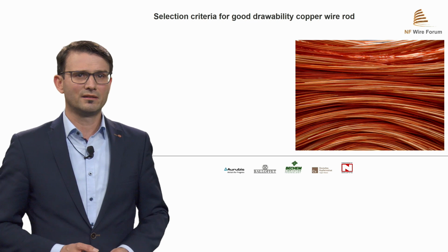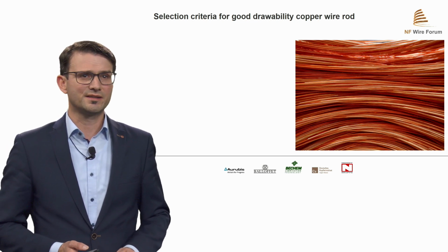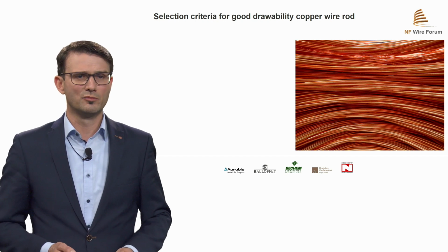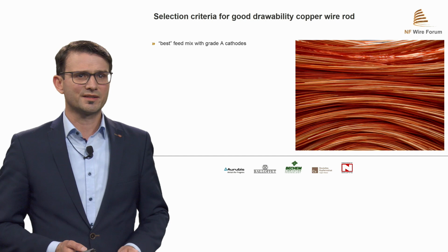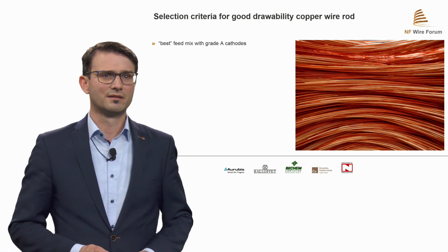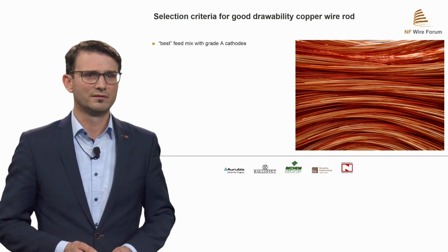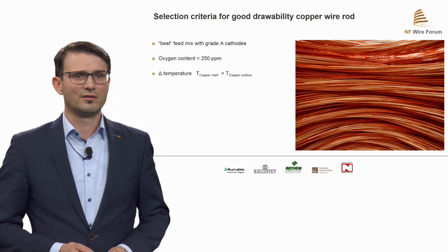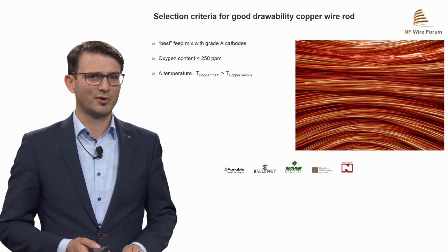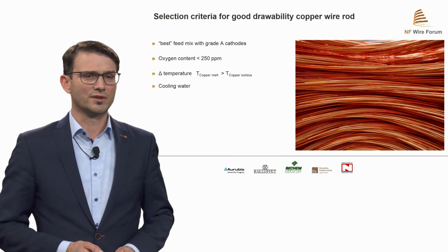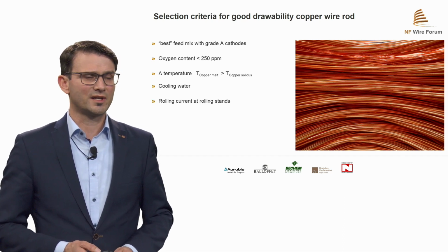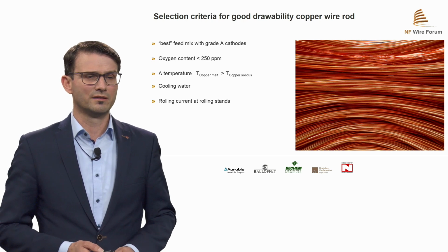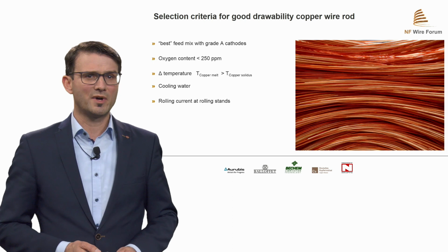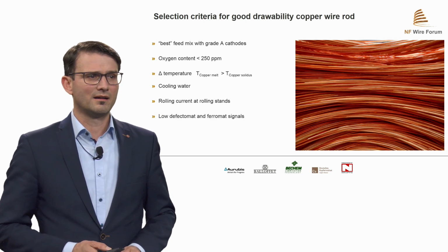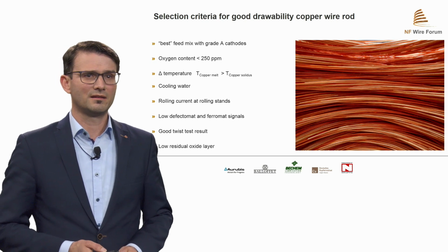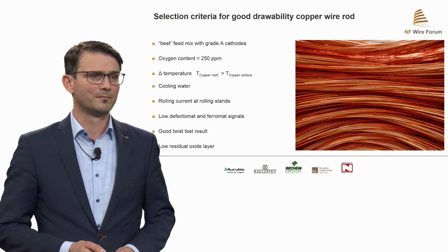Please see here criteria which are important and are the basis for a successful drawing process of Aurubis Rod, Rhine Rod. As mentioned before, best feed mix with grade A cathodes, oxygen content below 250, a delta temperature of copper melt versus copper solidus temperature, cooling water min-max values, rolling current at the rolling stands as well in min and max values, low Defectomat and Ferromat signals, good twist test results, and last but not least, low residual oxide layer.